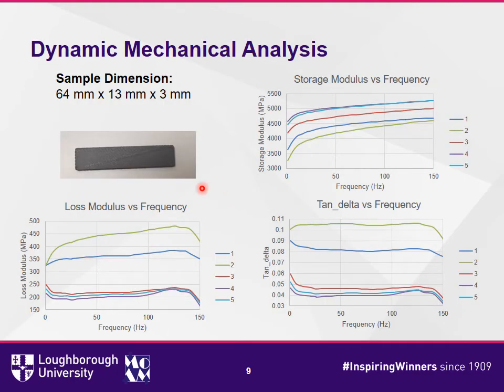Finally, the dynamic mechanical analysis under 3-point bending test was carried out as per ASTM D5023. A frequency sweep was carried out from 0 to 150 Hz. The average storage modulus ranged from 4 gigapascal to 4.5 gigapascal. The loss modulus ranged from 200 megapascal to around 250 megapascal. And finally, the tan delta of the material averaged around 0.045.